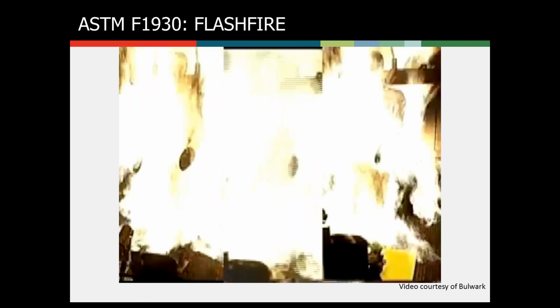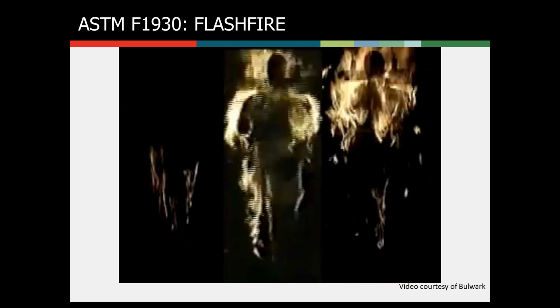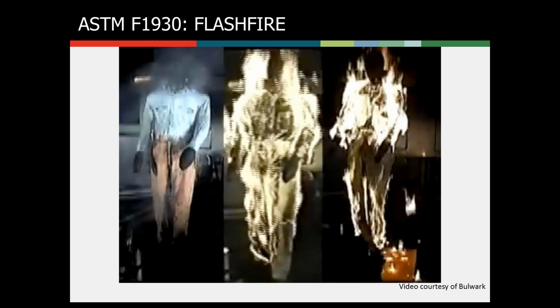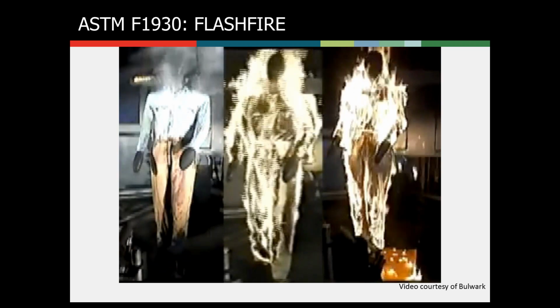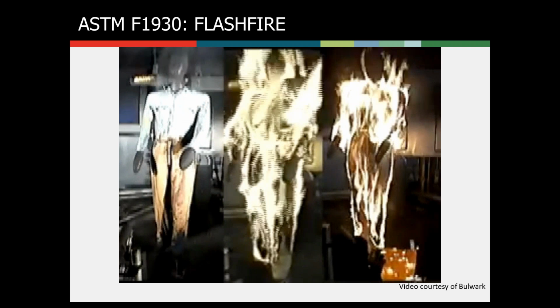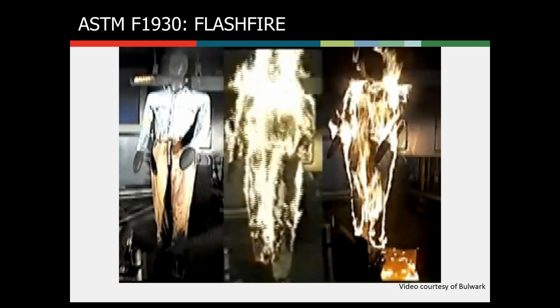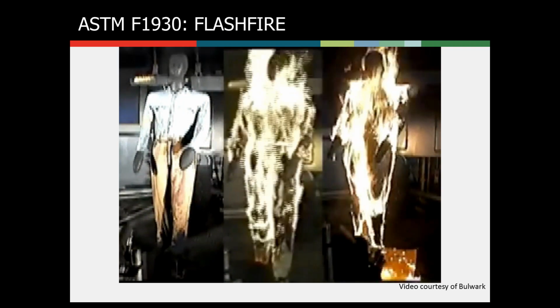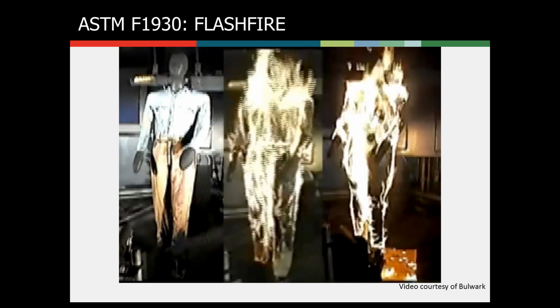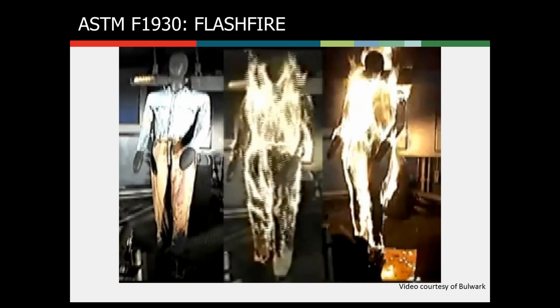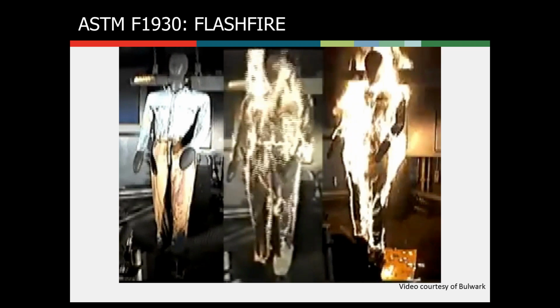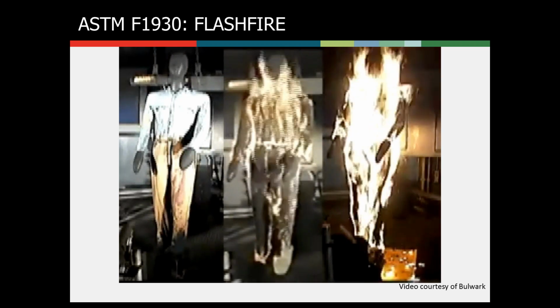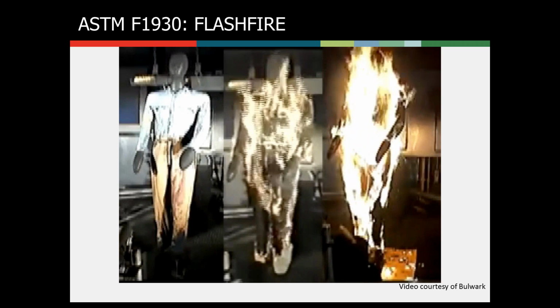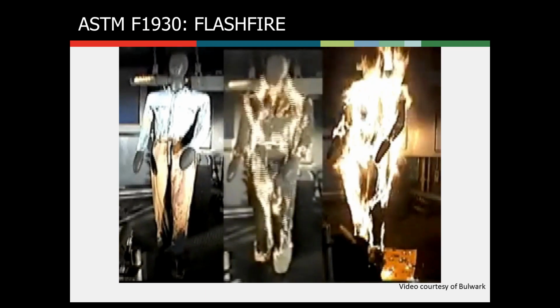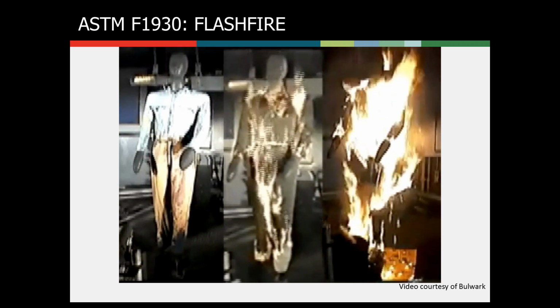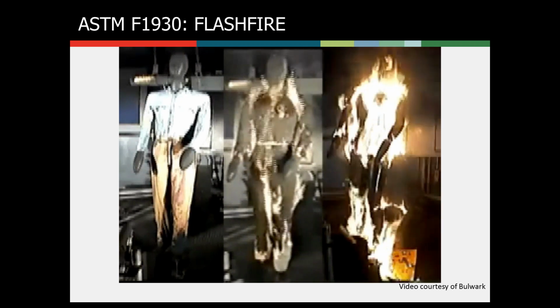It's done on a full-scale mannequin. The mannequin is instrumented with over 100 heat flux sensors all around its body. The fire exposure is created by 8 propane burners, creating a heat flux of around 84 kilowatts per meter squared, so a significant fire source, for 3 seconds. Underneath these garments, the mannequin is also dressed with cotton briefs and a shirt. After the exposure, the sensors measure how much heat transferred through the material and how much of a burn you would anticipate a person getting from this flash fire exposure.